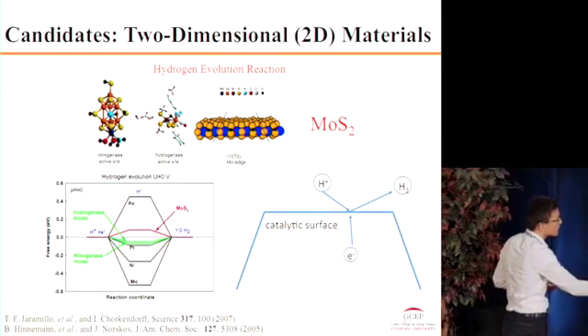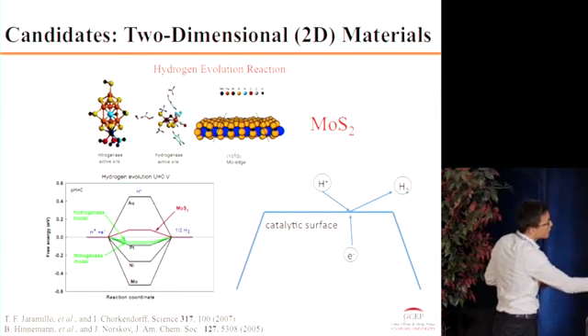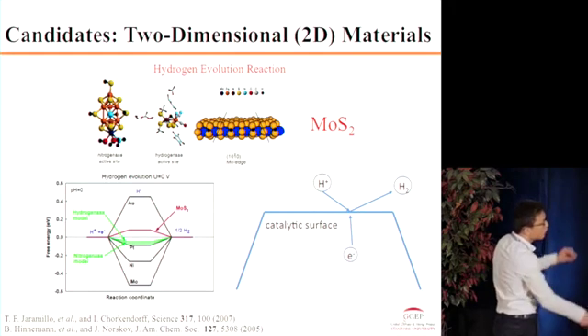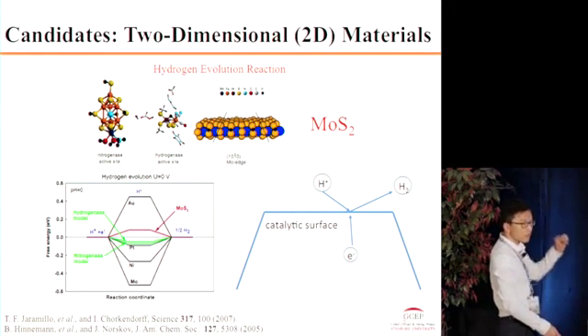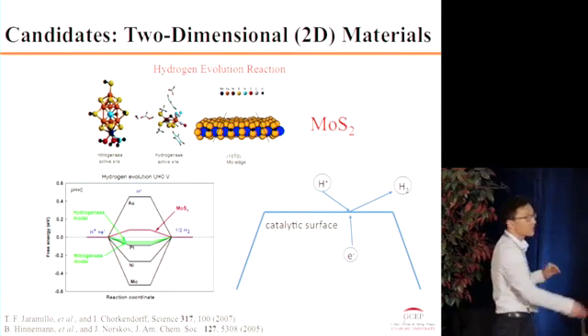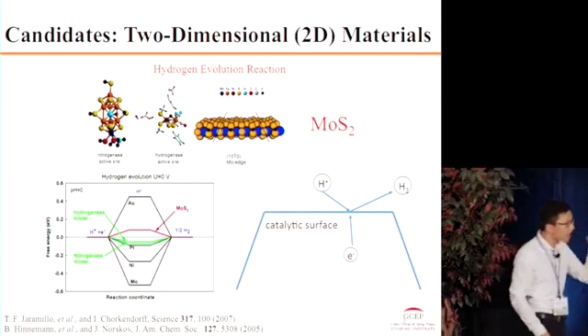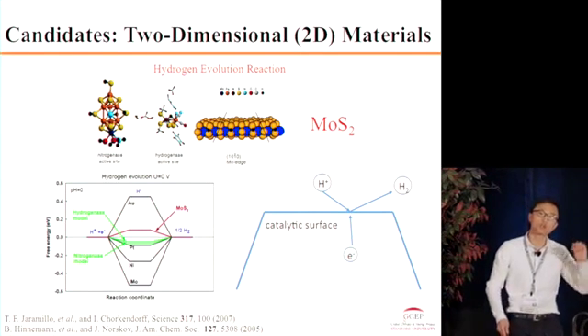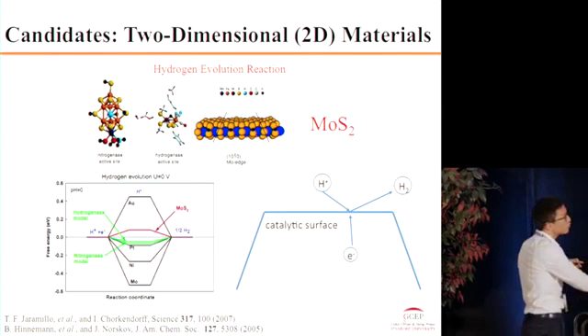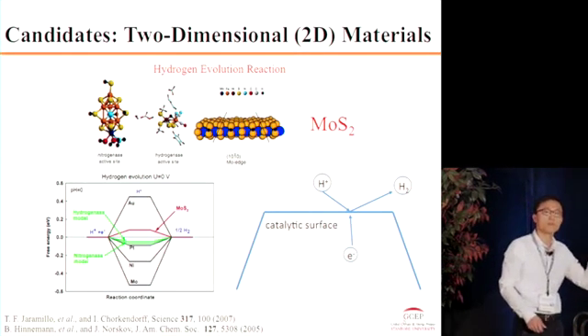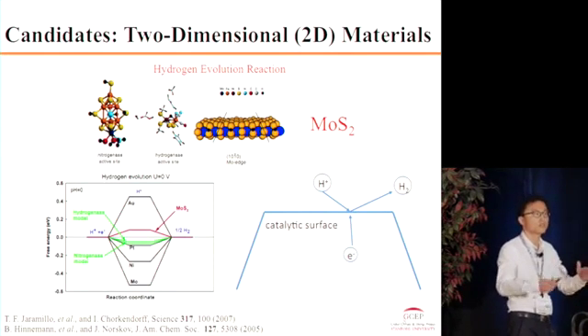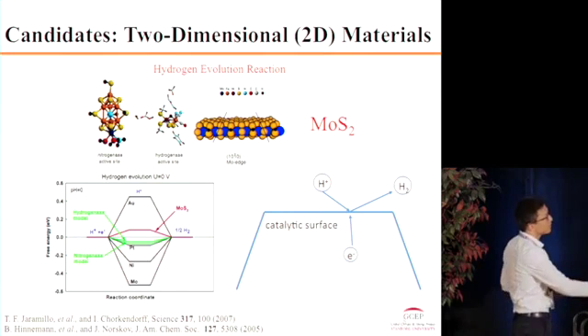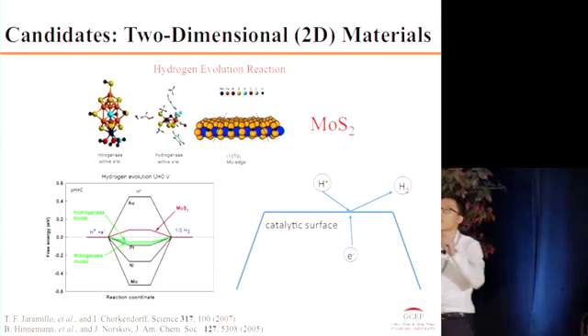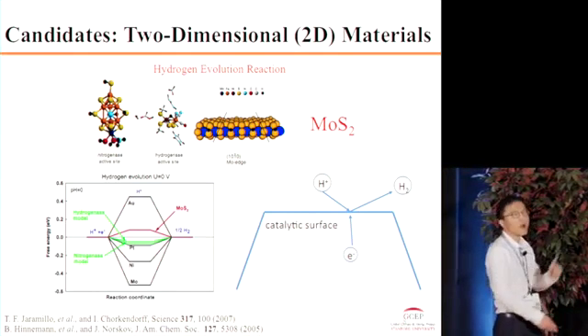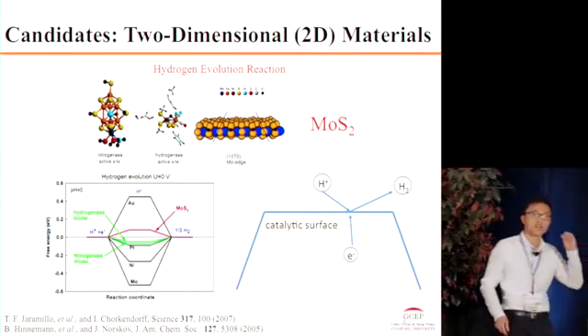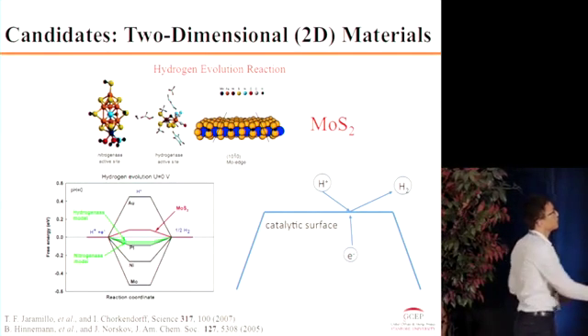As we can see from the free energy diagram, molybdenum sulfide has a very low free energy that is very close to zero, which is similar to platinum, which means that on the edge side you have a bonding which binds the hydrogen not too strong and not too weak. If you bind the hydrogen too strongly, you have a problem that when the hydrogen is released, this step will become rate limiting. But if you bind the hydrogen too weakly, there will be a very slow step for the electrons to pump into these hydrogens. So the best catalyst is one that binds the species not too strong and not too weak.